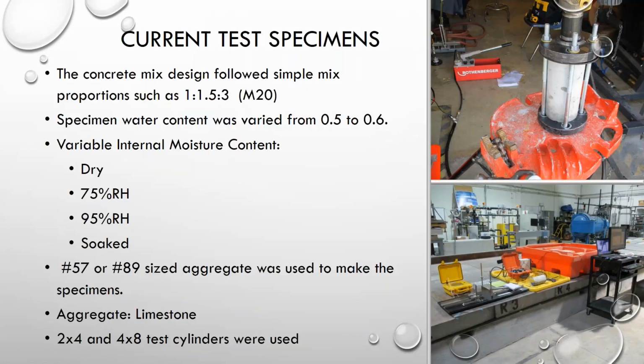The current testing we've done is we use a concrete mix equivalent to an M20. The specimen water content was varied between 0.5 and 0.6. They were kept at different moisture contents between dry, 75%, 95% relative humidity, and also soaked. Also, we had 2 different aggregate sizes, a #57 and a #89. The aggregate was limestone, and we made 2x4 and 4x8 test cylinders.